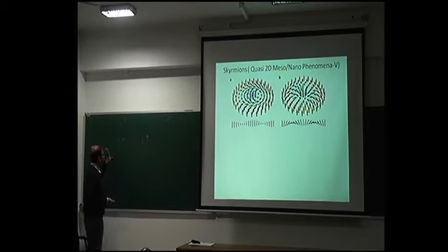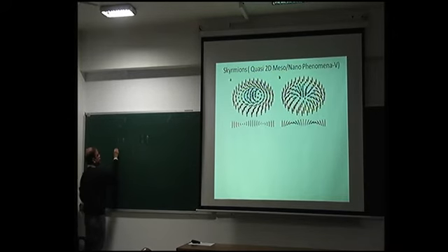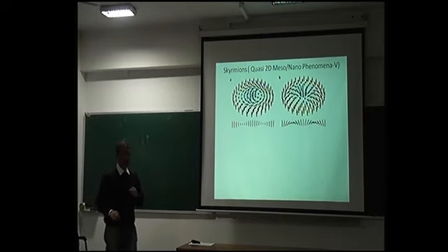Now, this magnetism can be divided into two parts. One is ferromagnetism, and AFM, antiferromagnetism, and we can call it isotropic. I'll explain why I call it isotropic. The interaction is isotropic. So you can model this ferromagnetism and antiferromagnetism with a Hamiltonian, which can be written as J Si dot Sj. This is the famous Heisenberg Hamiltonian, and with this Hamiltonian, you can explain most of the mechanisms of ferromagnetism and antiferromagnetism.